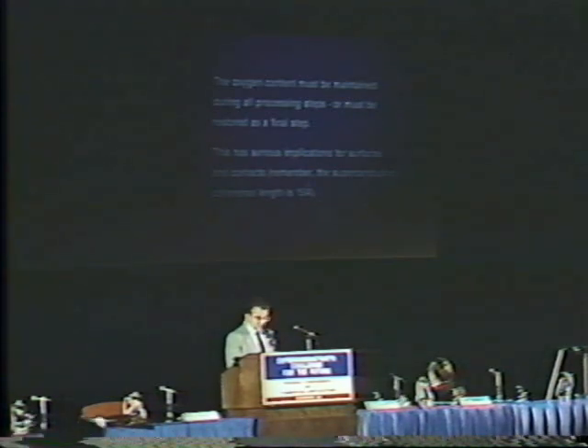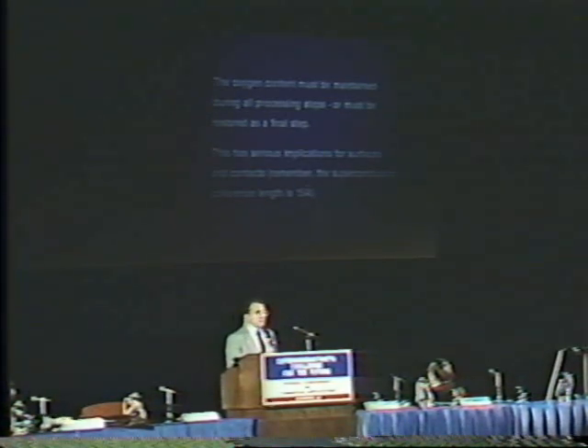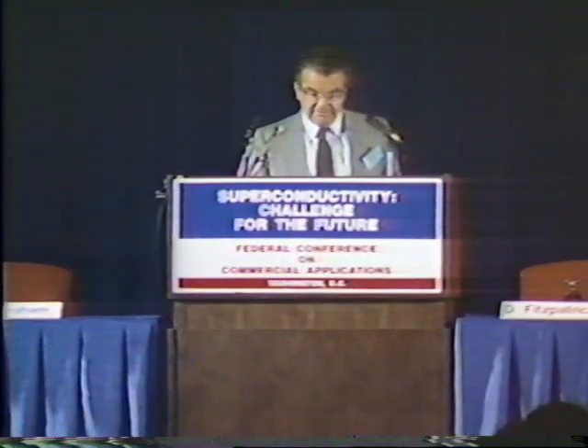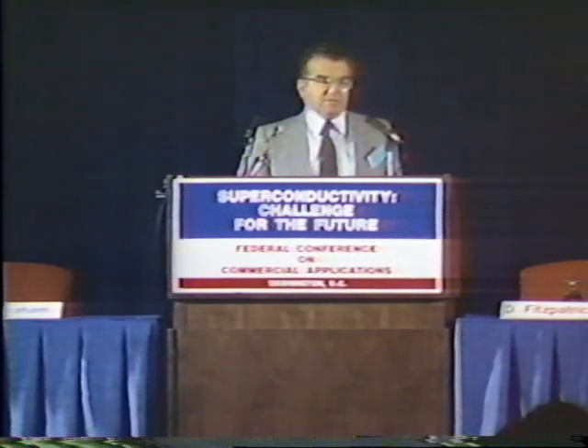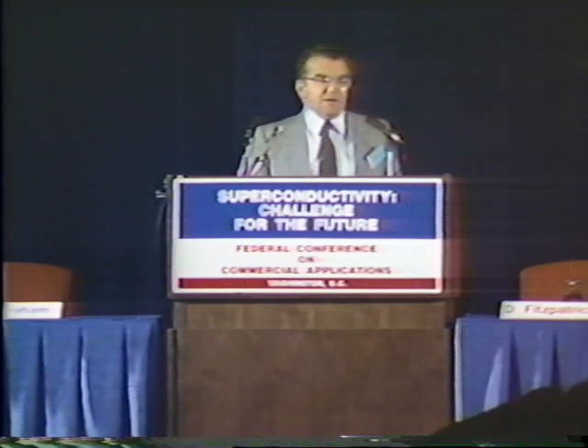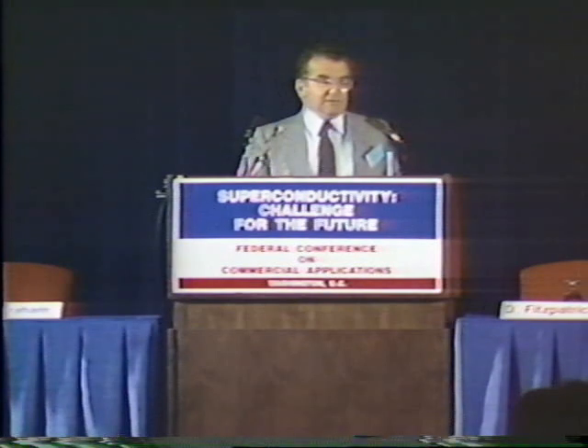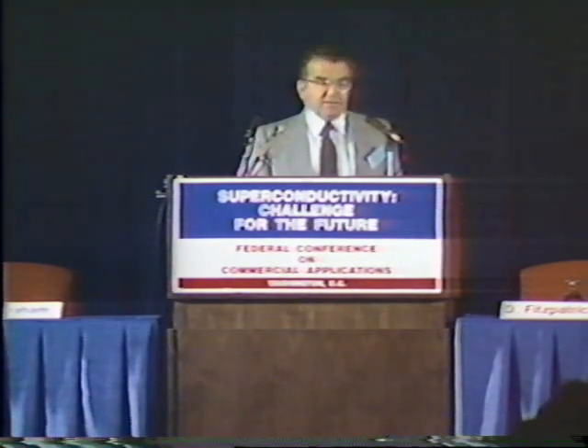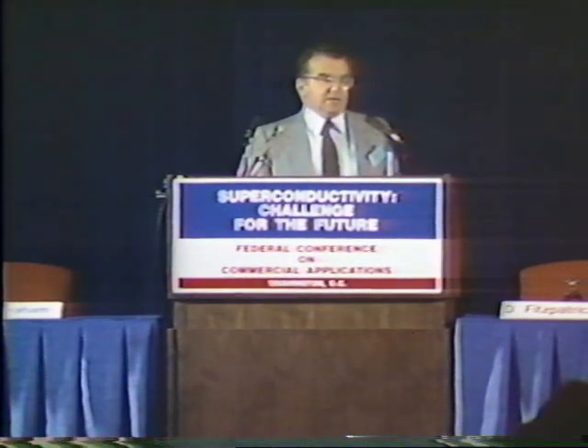And this has particularly serious implications for surfaces and contacts to the material. The applications there would be Josephson junctions, cavities, contacts. Remember yesterday you were told that the coherence length in these materials is 20 angstroms or less, 15 maybe. That means if you have a surface of the material in which you deplete oxygen over 20 angstroms, which is only one or two atomic cells of the material in the long direction, the C-axis, then you have no superconductivity. In fact, you have an insulating layer over 20 angstroms.